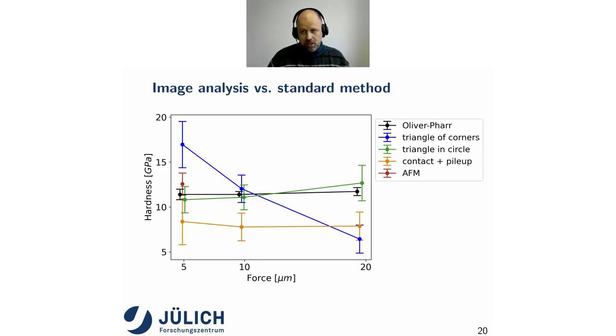If we look at the orange line, for example, we have the contact and the pileup. In these cases, our contact area is overestimated, and so it makes sense that our line is under the reference measurement. If we look just at the corners of our indents and use that to measure our contact area, that's also not very accurate, because we have cracks in the silicon. Also, these points are not so precisely identified, so that is also not the method of choice.